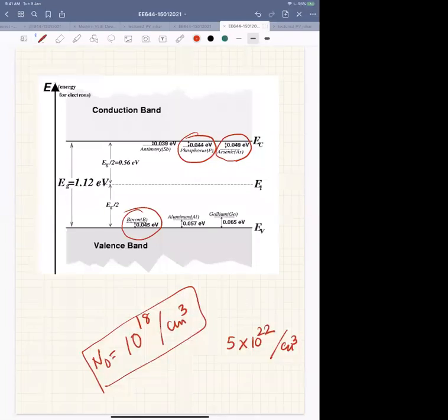We also discussed that if there are multiple energy states, then they form a band. So if you go on increasing the doping, the defect states will not be discrete, they will form a band, very close to each other. Because for phosphorus this is 44 millielectron volt, and if you create another defect state, it will be very close to 44 millielectron volt, because it cannot be at exactly 44 millielectron volt since there is already a defect state there. So similarly, if you go on increasing, they will slowly form a band.